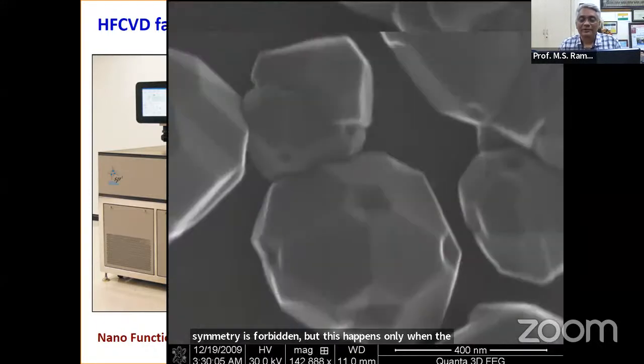Normally in crystal growth, 5-fold symmetry is forbidden, but this happens only when the crystal size is below 400 nanometers. After that, the 5-fold symmetry vanishes.